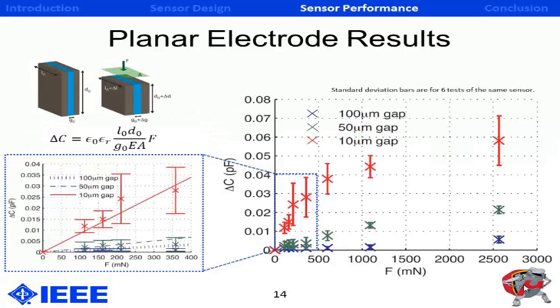These are the results from the planar electrodes. On the right-hand side, the y-axis is change in capacitance as a function of force. And on the left-hand side is a blow-up of the low force region. And the lines are the analytical models that were developed. These are for 3 different sensors, 3 different gaps of 10, 50, and 100 microns. And as you'd expect, we found about an order of magnitude higher sensitivity in the 10 micron gap over the 100 micron. In addition, it's important to note that at higher forces, there is a decrease in sensitivity, which could be due to the material reaching a saturated state in which it can compress no further.